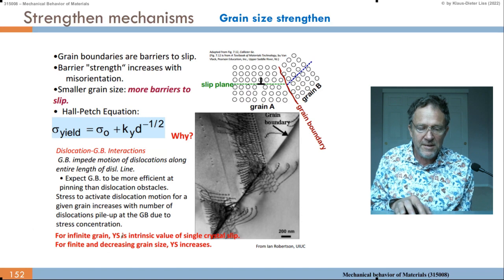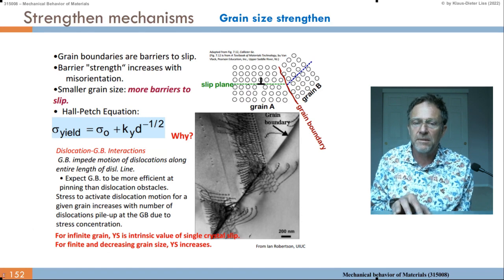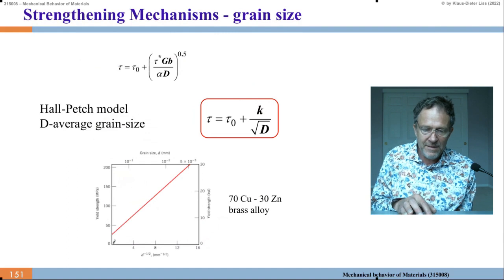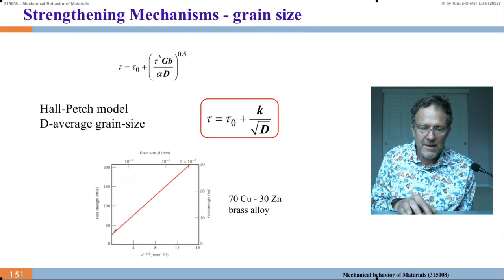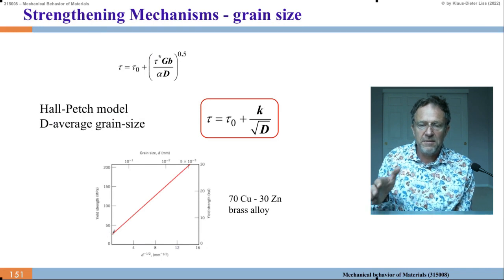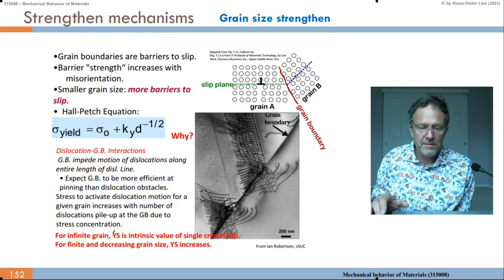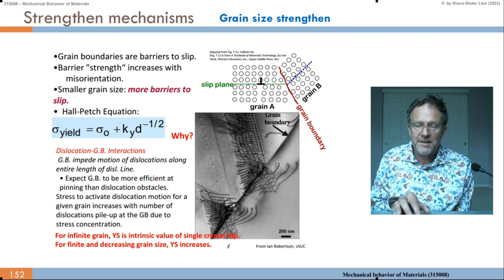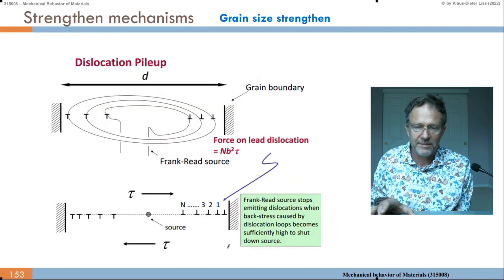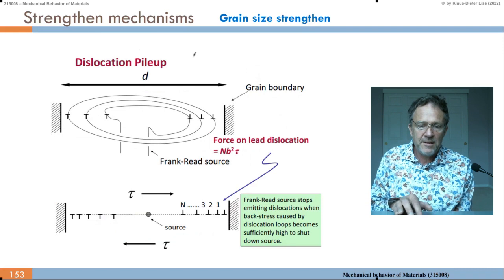So for infinite grains, the yield strength is the intrinsic value of the single crystal slip. Yeah, infinite grain size is here. Then we have the threshold stress, the shear stress we need to apply to move dislocations at all. It's not zero. And then for finite and decreasing grain size, the yield stress increases, as shown. Here's this dislocation pile up.